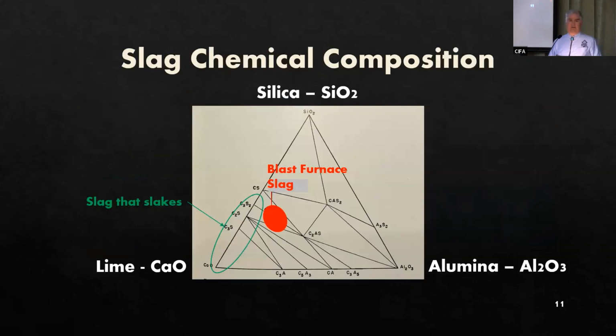So early scientists in the 18th and 19th centuries, when Cornwall Furnace was starting to fire up, had a difficult time characterizing the composition of the slag for a couple of reasons. One was the primitive state of chemistry as a science back then. And another was this complex relationship between the various components of the slag. For example, if the amount of lime increased, then the amount of alumina or silica would have to decrease proportionately.